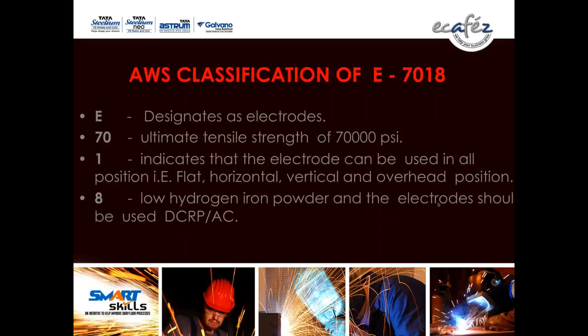Check the example, AWS classification of electrode E7018. E designates electrode. The first 2 digits, 70, mean ultimate tensile strength of 70,000 psi. Third digit 1 indicates that the electrode can be used in all positions: flat, horizontal, vertical and overhead. And the last digit 8 stands for low hydrogen. The coating contains low hydrogen iron powder, and the electrode should be used in DC reverse polarity and AC also.